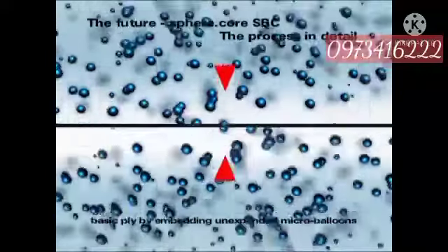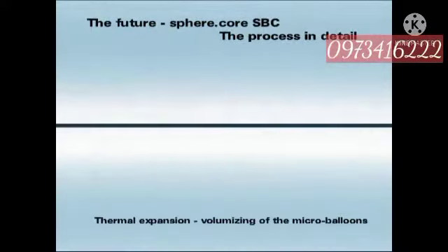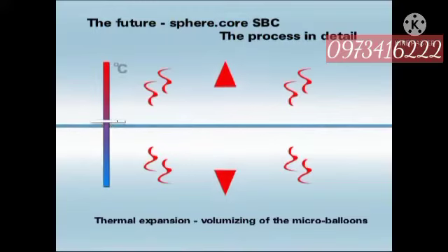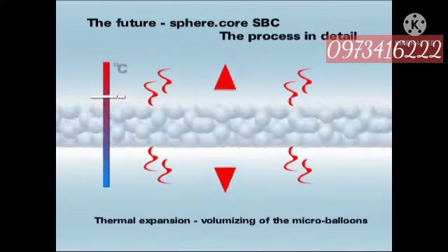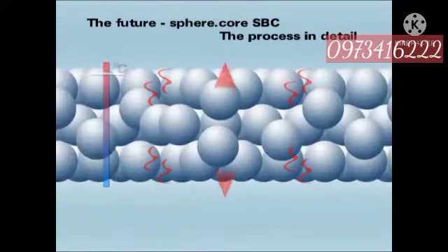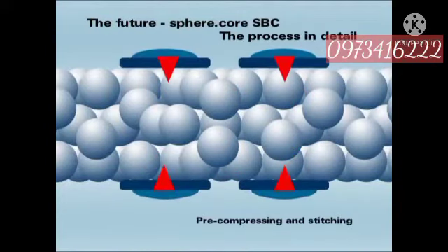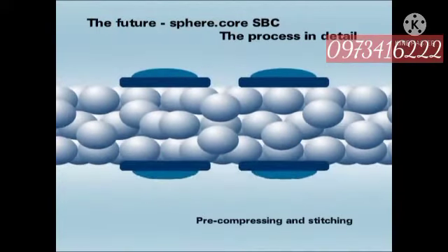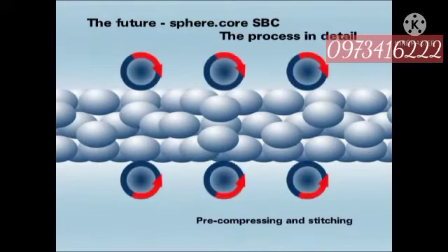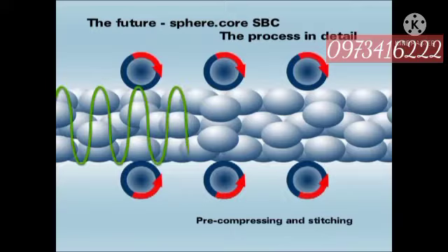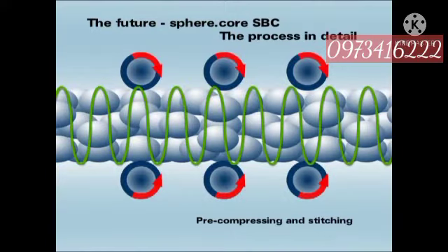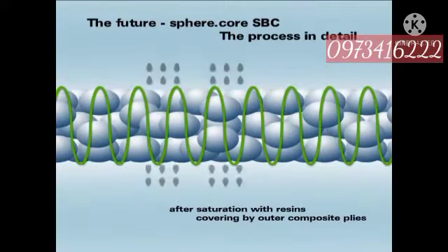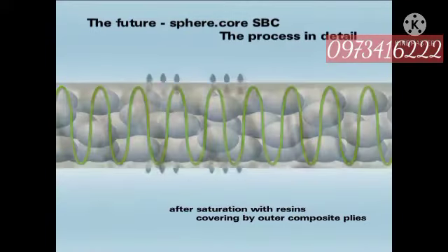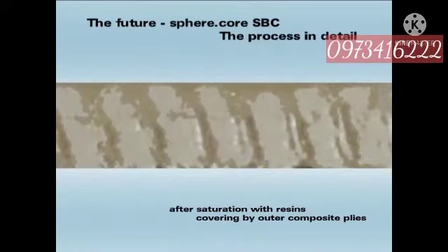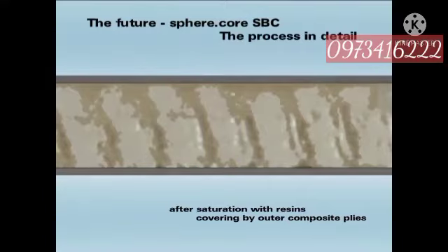Unexpanded thermoplastic microballoons are embedded into the basic glass ply. By a thermal process, the microspheres are expanded to the desired thickness. This core layer, called sphere core S, must be compressed by a mechanical compression process and held under compression by a following stitch bonding process. The result is a mat called sphere core SBC, stitch bonding compressed, with a reduced resin absorption. The specific gravity of sphere core SBC is about 400 kilograms per cubic meter.